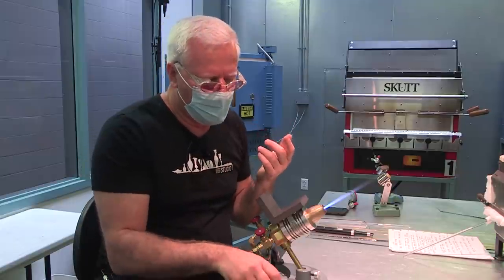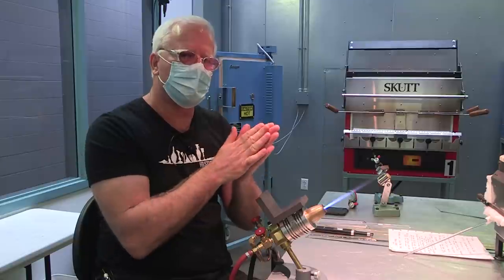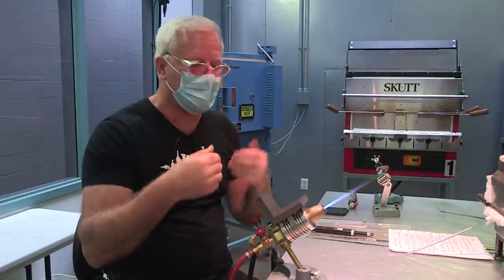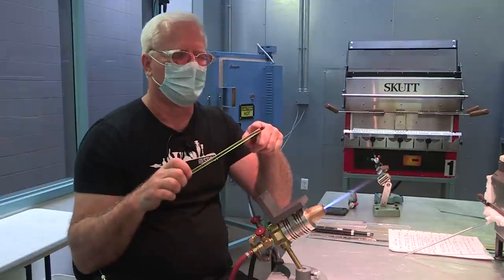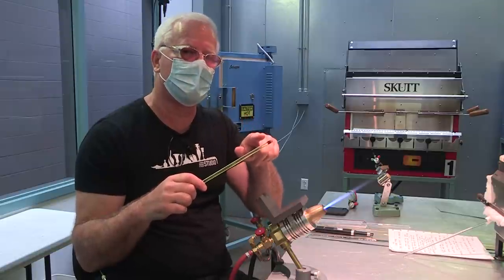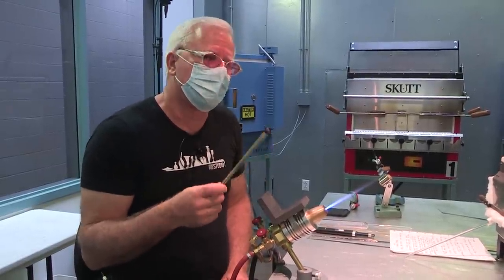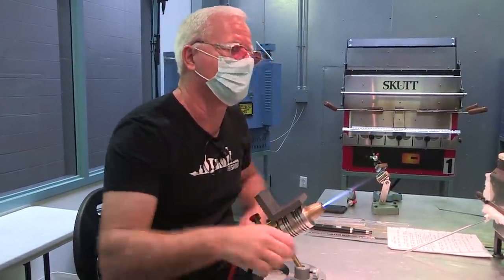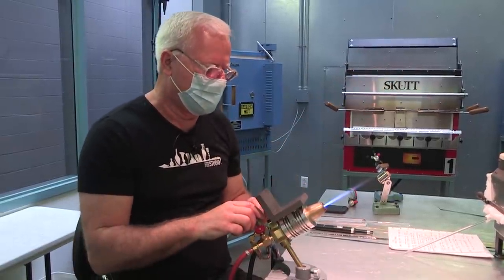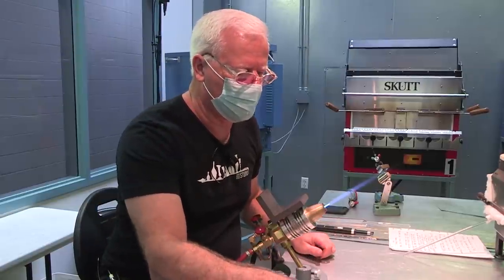Remember, they grow as wavelengths of light that we can see. And so once they're suspended, great, but once you start to cool it, then they start to grow back into the body of the glass, and that color spectrum starts to bloom. And that's exactly why we see this from the ambient heat, right? The first stages are your reds, your oranges, your yellows, and you see that without any type of actual reduction flame there. So I suppose you could try it. I would be interested to know how that would work if you were trying to do it up here. I think it might take you a lot longer. But I personally have never done it, so it could work. Who knows?